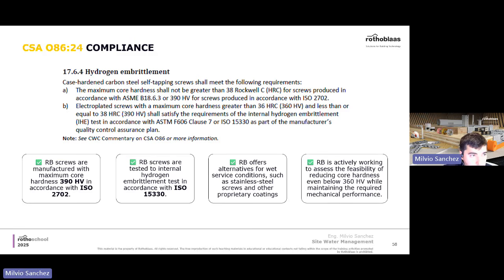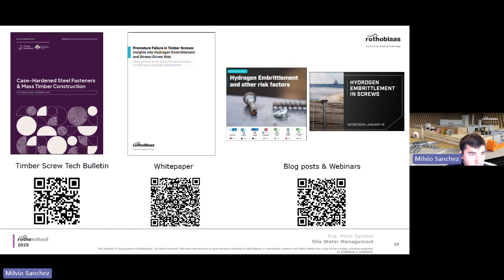The CSA O86 is the first standard worldwide to talk about specific hardness for screws in the market. There you may find that case-hardened carbon steel self-tapping screws shall not be greater than 390 Vickers, and they have to satisfy the requirements of the internal hydrogen embrittlement test. So this is what Rothoblaas does. We have screws below 390 Vickers in accordance with ISO, and we perform internal hydrogen embrittlement tests on the screws as well. This is really relevant, and we hope to see that in other standards worldwide.